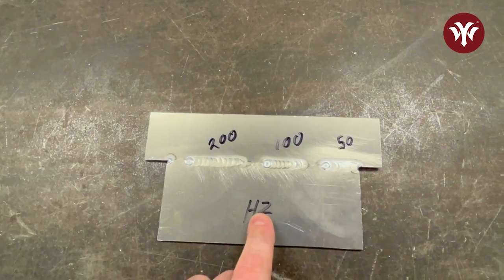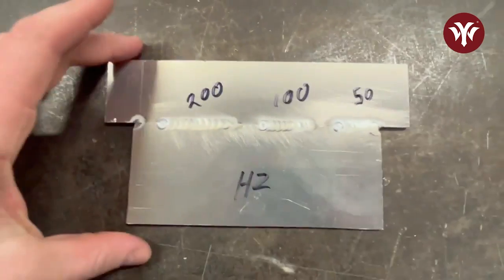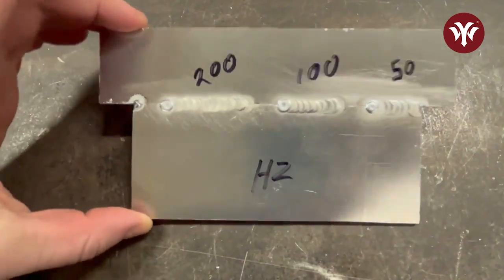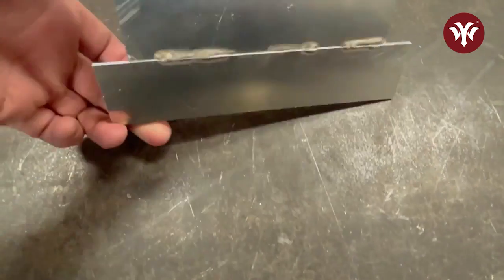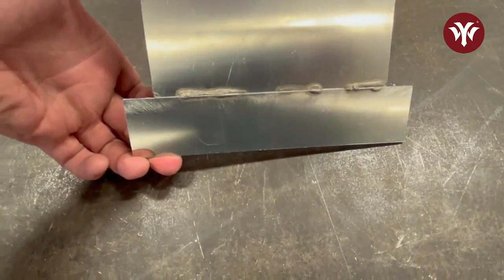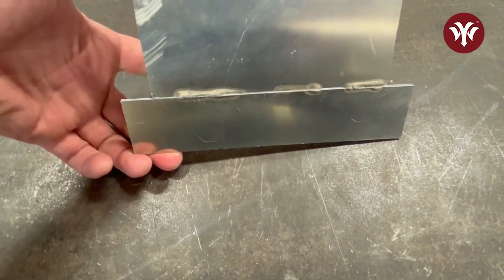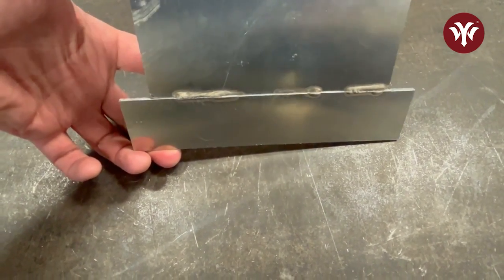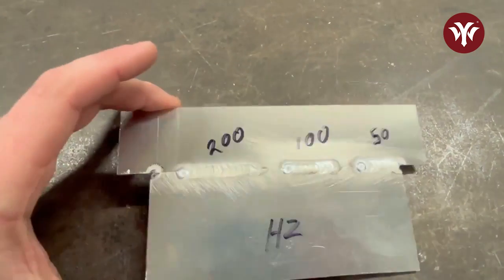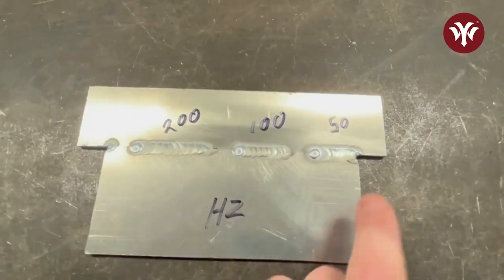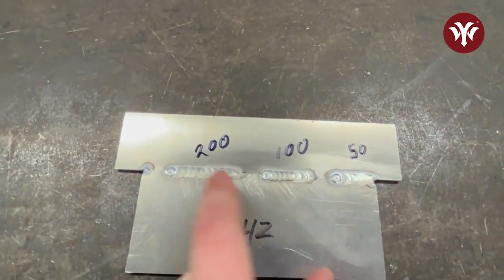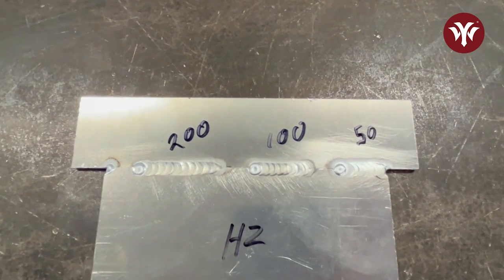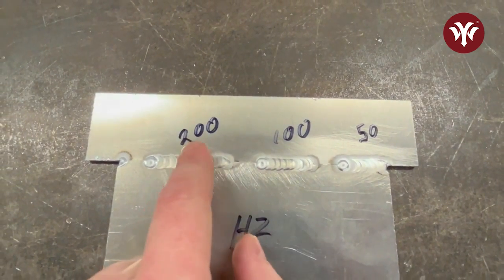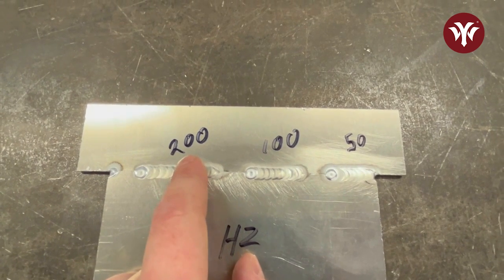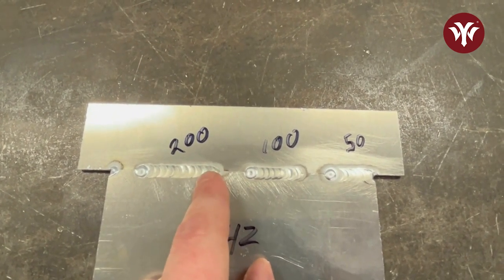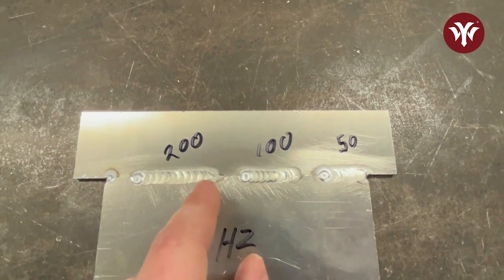Okay, here's the coupon that we were playing with frequency. As I thought, and it's hard to show you here, there's very little difference in the look of these welds. Penetration varied. I wasn't really paying too much attention to that, so I can't really make a comment on penetration versus frequency. But what you could really tell was the sound. 50, 100, and 200 Hertz. You could definitely hear the difference in those welds. And my understanding is that as you go to higher frequency, that allows you to weld on thinner materials. You get more cleaning cycles, and it should penetrate a little bit better.